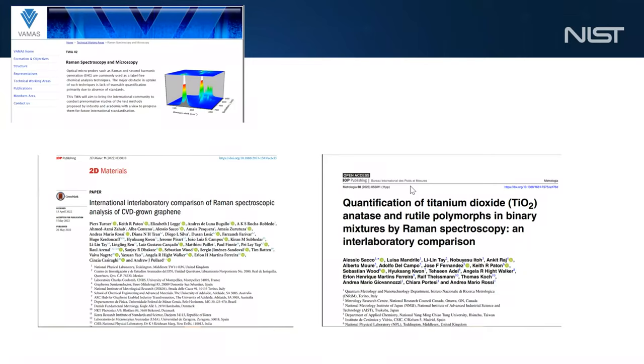What's great about these studies is we can determine the errors and where likely they come from in the measurement or in the protocol. And so in the first case, where we were doing Raman spectroscopy, dear to my heart, I'm a Raman gal, of CVD grown graphene, what we found out was often people are not calibrating their instrument over large Raman shift distances, I'll call it. So in Raman, many of you know there's a 2D peak and a G peak. Well, they are separated by over 1,000 wave number shift. And if your instrument does not have a flat response over that large area, you can't take a ratio of the two peaks and get a meaningful number. So it was important to learn that sort of thing.